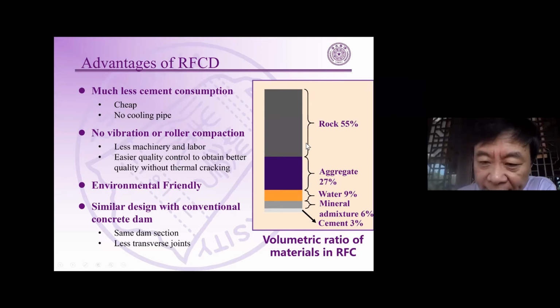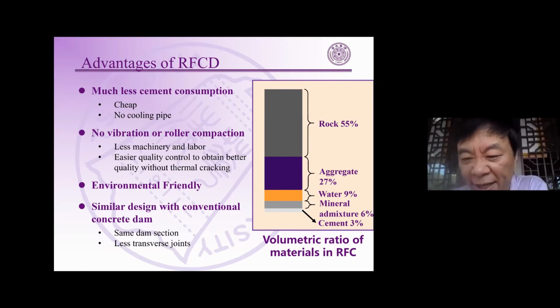You can see this is the volumetric ratio of materials in rock-filled concrete. About 55% in volume is large rocks, with grain size larger than 300 millimeters. The maximum grain size of the rocks in a dam may be 800 millimeters or even 1 meter, even 2 meters if you can transport it. And the other 45% in volume is filled by the self-compacting concrete. But in the self-compacting concrete, we have 24%